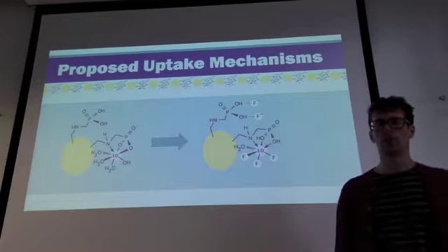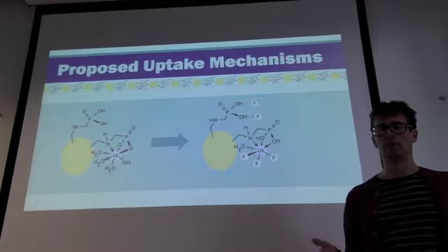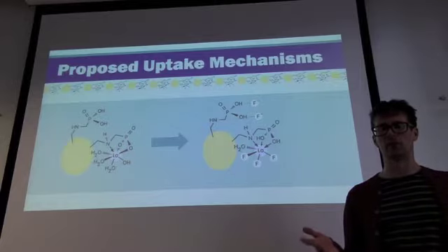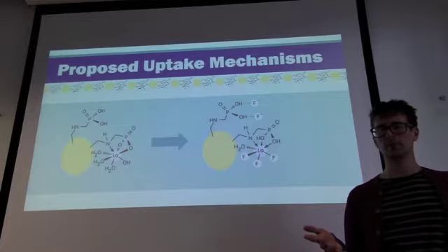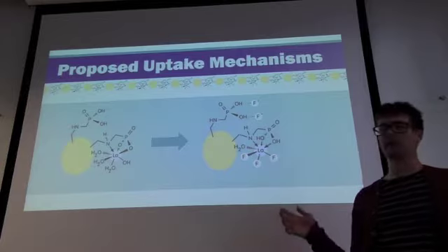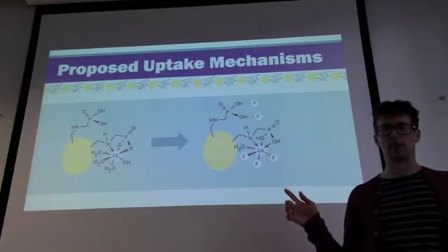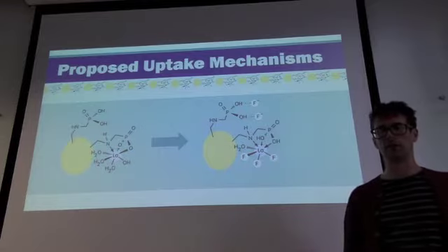How do we know this? Well, we can calculate an estimate for the number of lanthanum ions that are transferred onto a gram of resin during preloading. We can also calculate the number of fluoride ions that are taken up during contact. Now you can see from the diagram on the right that each lanthanum ion can only accommodate 3 fluoride ligands, otherwise the species formed is simply not chemically sensible.